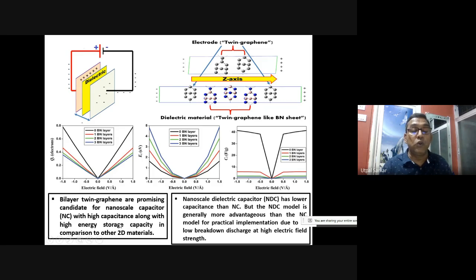Which is visible here. So these are the nanoscale dielectric capacitor, because we are putting this here. However, this is the nanoscale capacitor, no dielectric media. So the nanoscale dielectric capacitor has lower capacitance than the nanoscale capacitor, and the NDC model is generally more advantageous than the nanoscale model for practical implementation due to low breakdown discharge at the high electric field. So though it is showing less capacitance, it is useful because you are using a dielectric medium in between.